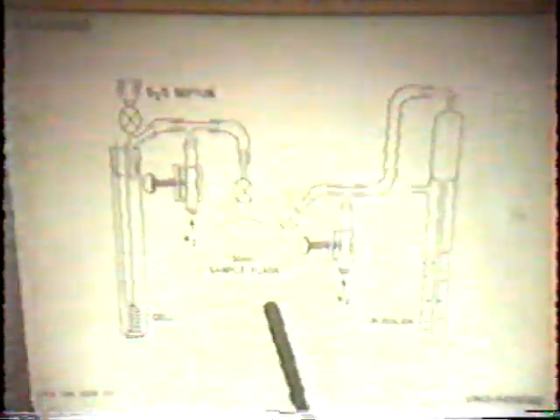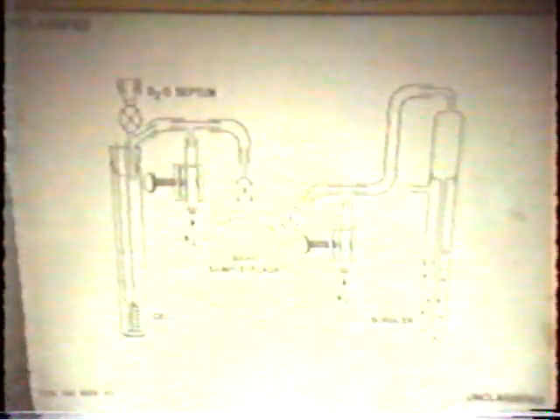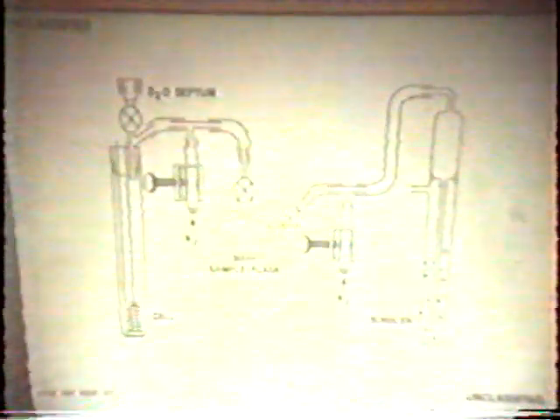Okay, our focus then is to measure the excess heat and try to correlate it with measurements of helium in the gases coming out of the cell. And the way we would do this, we have the electrolysis cell here. We're not showing the calorimetry part of it, but just the electrolysis cell. We do electrolysis, the gases go up out the top, and they flow through this flask, the 500 milliliter volumetric round bottom flask, with the inlet and outlet and the stopcocks. And then it goes through an oil bubbler because you want to keep it always under positive pressure so there's no air that can get in. And then it goes from the oil bubbler out into the atmosphere.